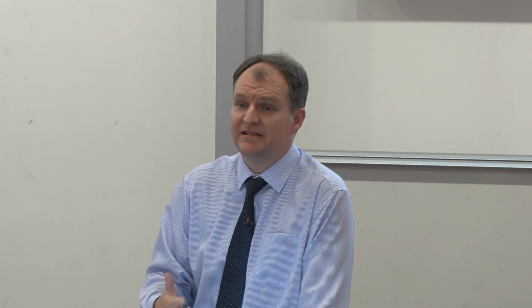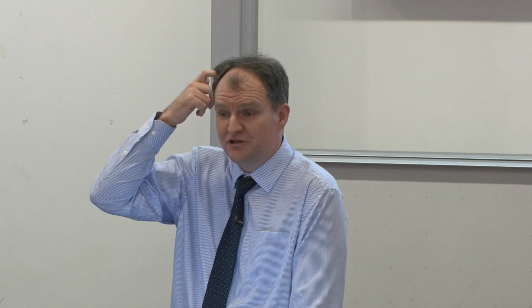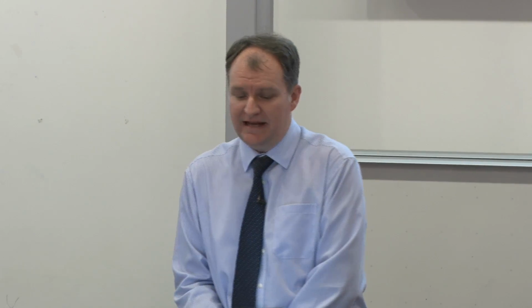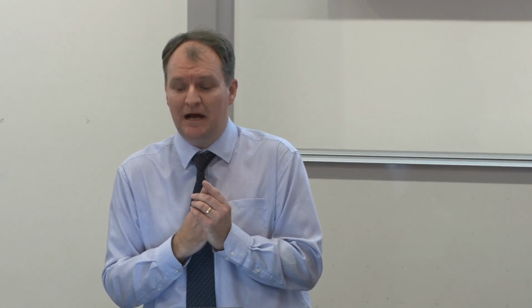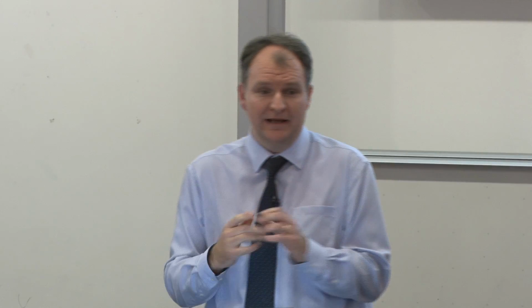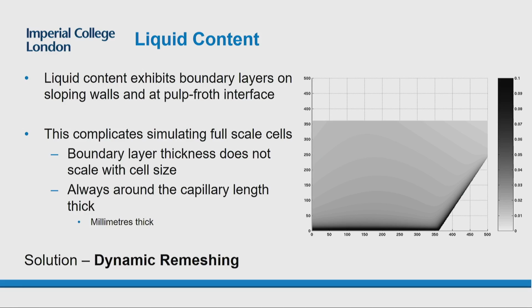And what we did was to solve this liquid drainage equation in a system which is a complex shaped geometry and which is flowing froth. And this is the sort of liquid behavior you get. And the most important feature of this is that when you have a flowing froth, you tend to get boundary layers forming in the system. You have relatively uniform liquid contents internally.